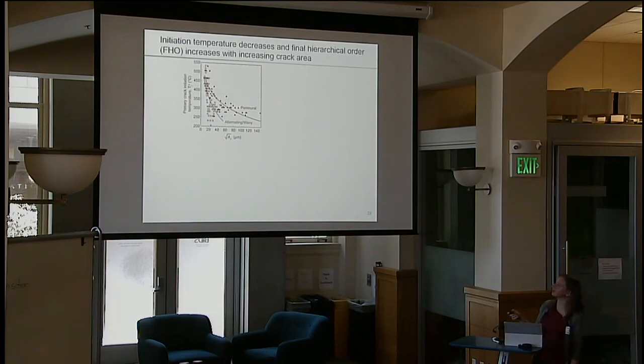So our first finding is that cracks that form in larger regions tend to form at lower temperatures, and also that alternating and wavy cracks tend to form in smaller regions. So for this case, we might actually want to optimize the fiber architecture to have smaller gaps between the fibers, which, as we saw before, is influenced by the behavior during impregnation and curing.